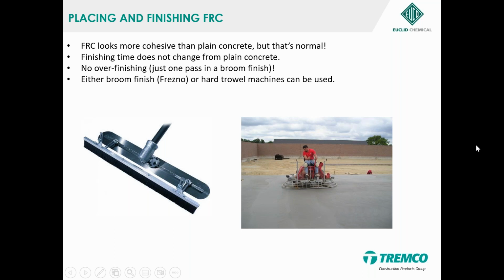Not only during application, over a period of time, say 5 years, you have an industry which is more abrasive, and the top layer comes off for whatever reason, then you start finding fibers popping up. Yes, it may happen with these fibers also, but it is not a big deal. It can be burnt, and you can put a fiber reinforced mortar or a proper concreting done properly, patch repair.